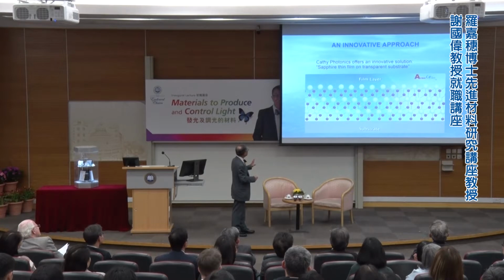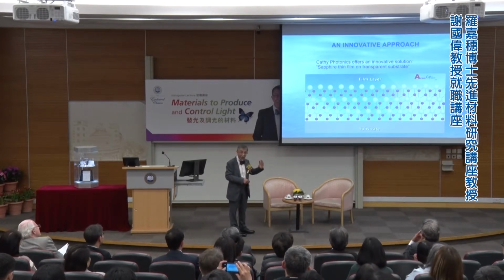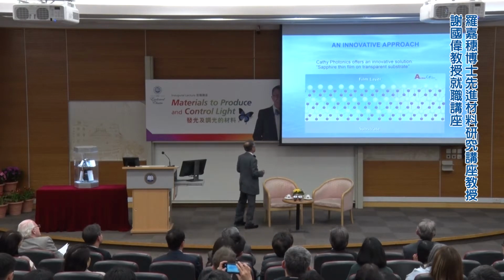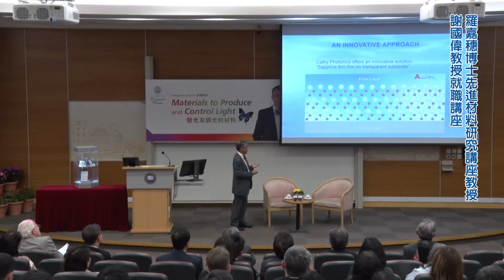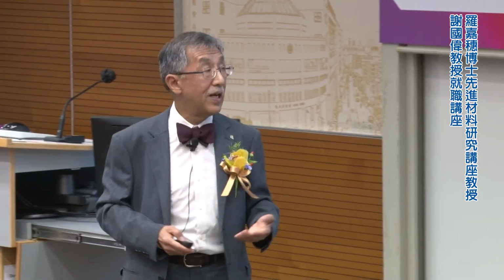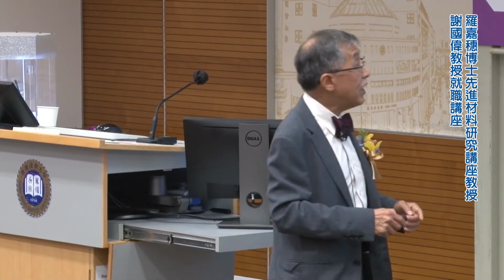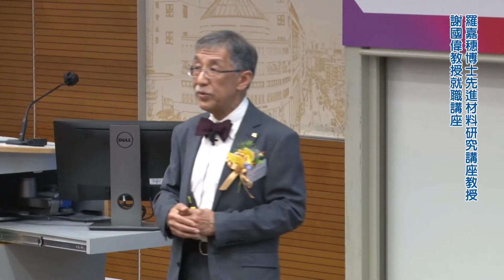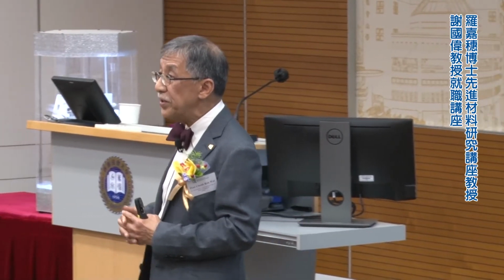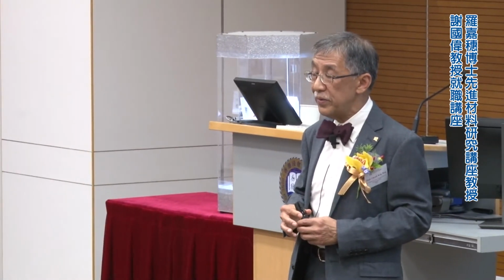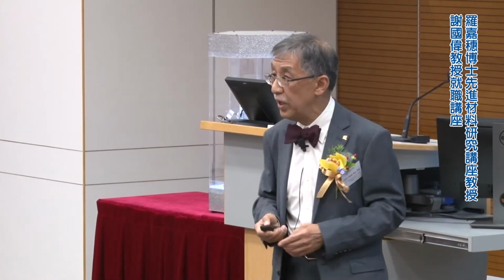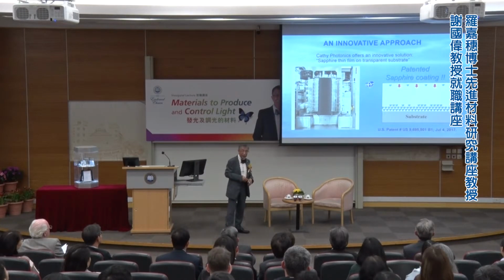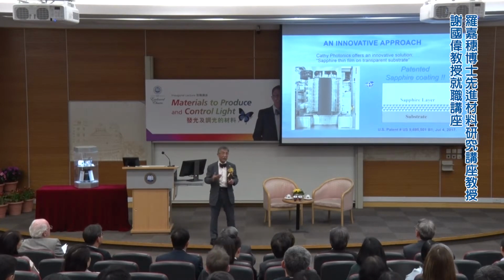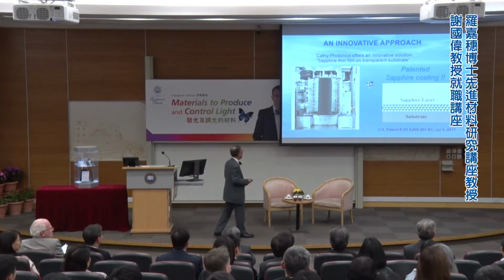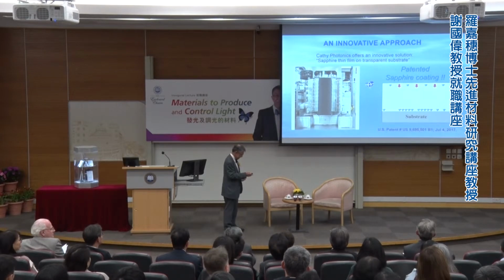Basically, we put on a very thin layer, less than a micron, several hundreds of nanometers of sapphire, and we are able to tune it so that it becomes as hard as almost the sapphire single crystal. We use, in fact, a quite standard industrial deposition method called physical vapor deposition. Most of the industry, in fact all of those doing some kind of thin film deposition, will have this kind of equipment. Therefore, we help them to adapt, and then they can start manufacturing it.